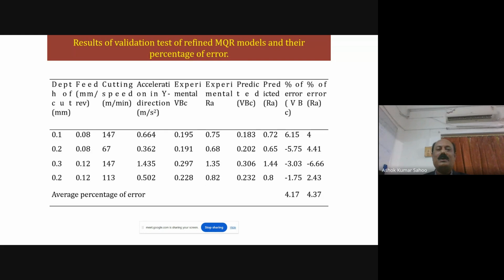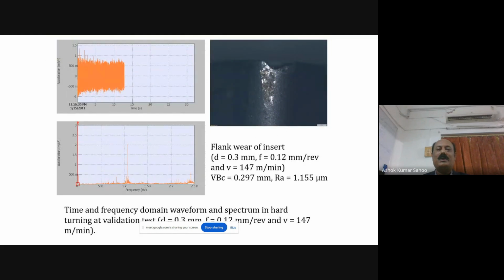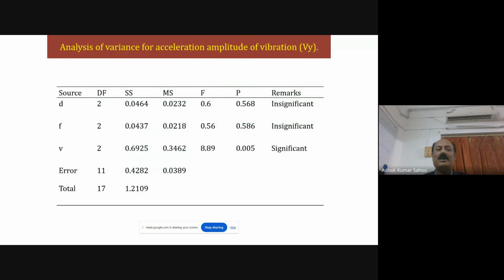And these models are validated with a different combination of the parameters of cutting speed and depth of cut, which was not chosen in the Taguchi design of experiment. Again, 3-4 experiments are conducted by taking arbitrary parameters of the cutting speed and depth of cut. So 4 experiments are conducted for validation, where we obtain the percentage of error less than 5%, and models are found to be significant and good. And these are the waveforms obtained. Cutting speed found to be the most significant parameter for the vibration.